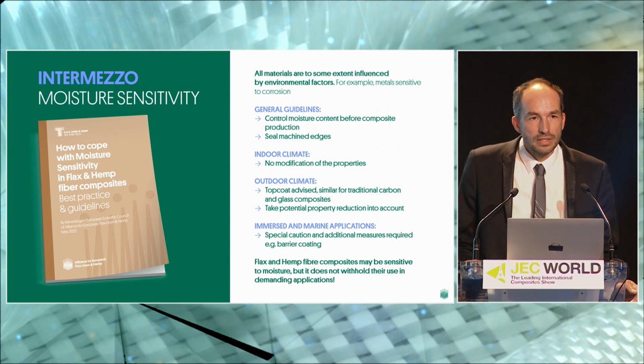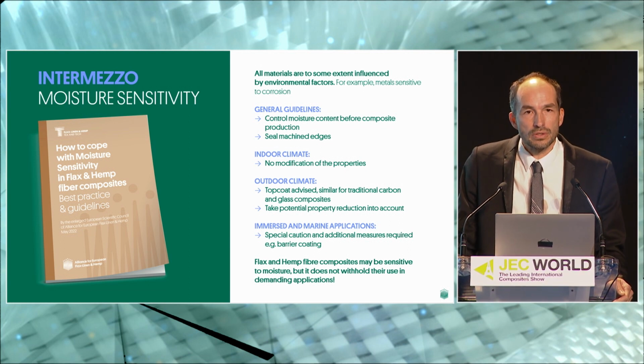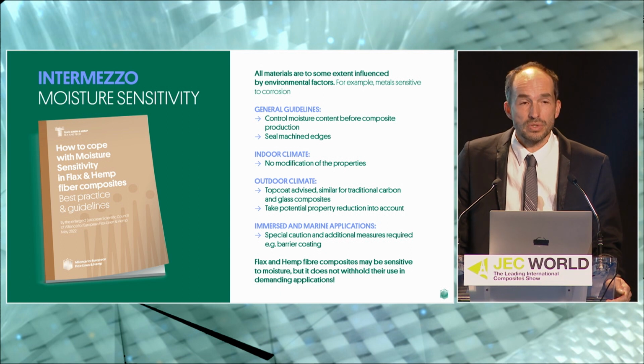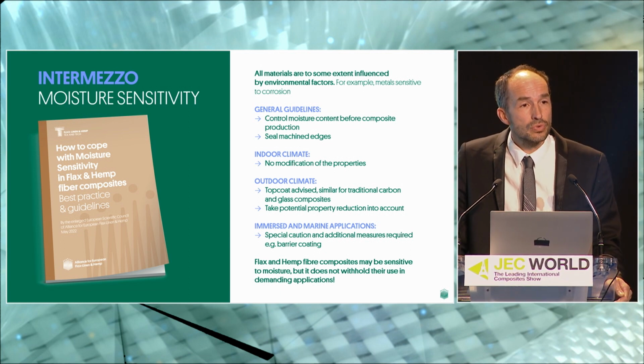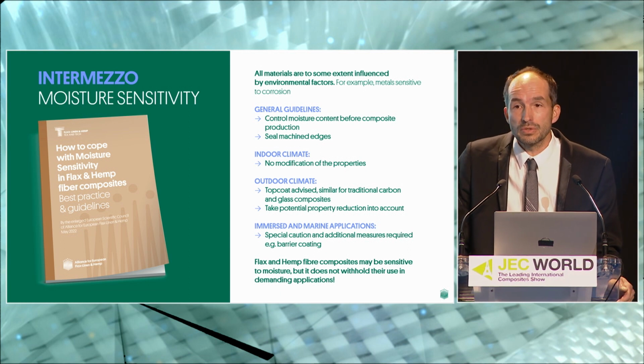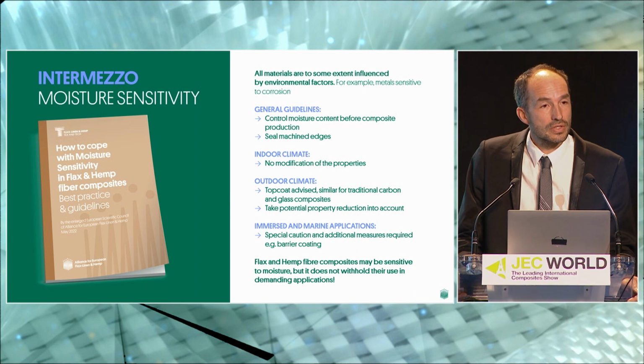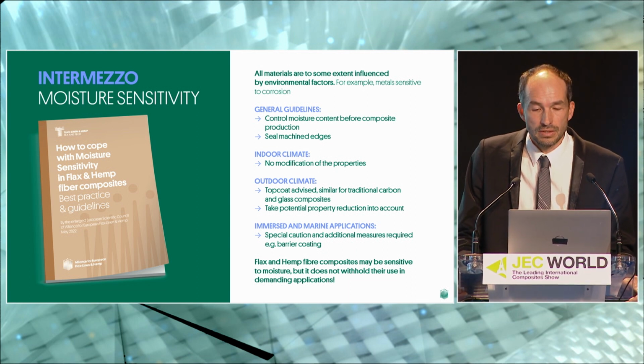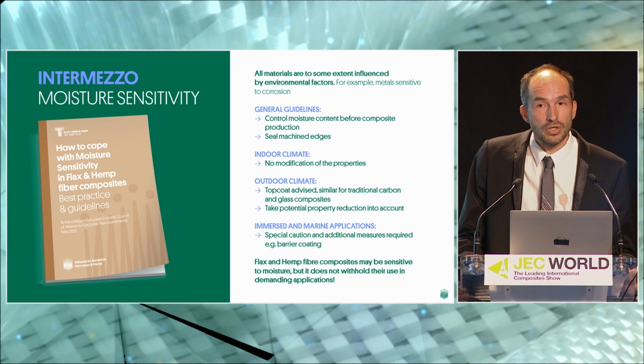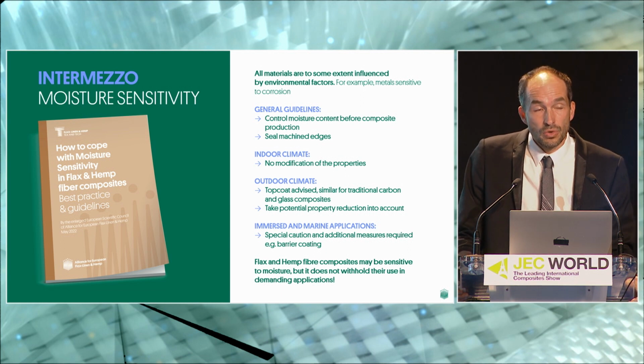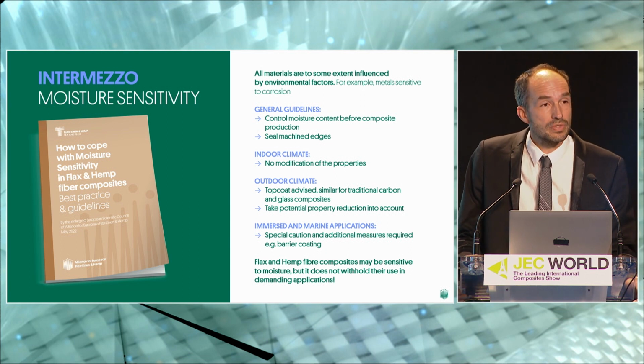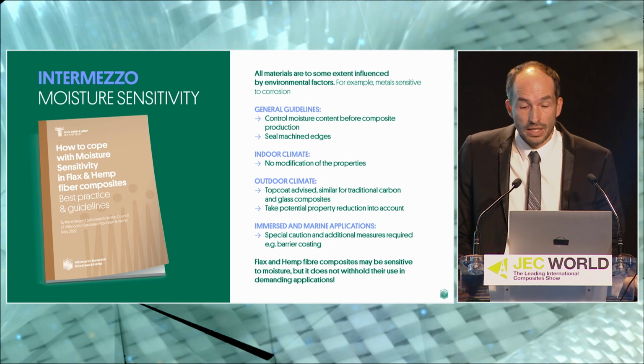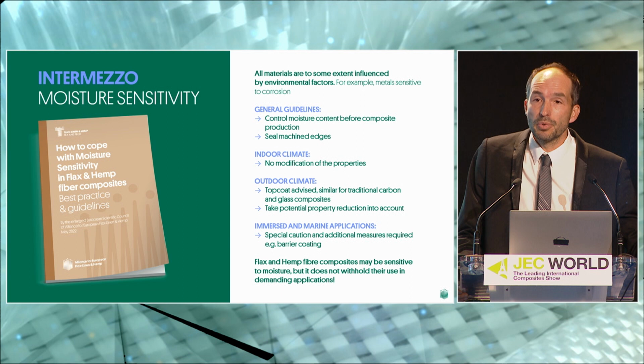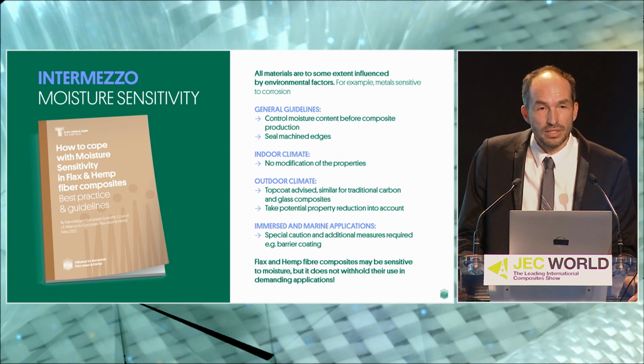Yes, indeed, durability is most of the time seen as a hot issue when talking about plant fiber composites, because it's true that plant fibers are sensitive to moisture, but as it was demonstrated, it does not prevent using this material for this type of application in contact with moisture and liquid water if you use the good protections or the good design considerations. So all the materials are more or less influenced by environmental factors. For example, metals are sensitive to corrosion, so it's the same for composites. We have to use the good protection depending on the type of climate or conditions to which the material is